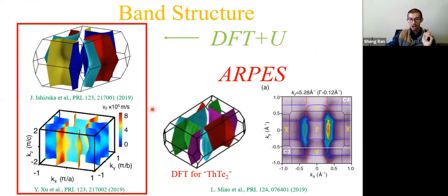Now, recently, someone proposed a different mechanism for this field-induced superconductivity based on the band structure. So for this uranium telluride, even though the sample looks 3D, when we do the DFT calculation or the ARPES measurement, you can really see there are four different sheets in the band structure. They're basically two pairs of parallel sheets. It's like a quasi-2D band structure.